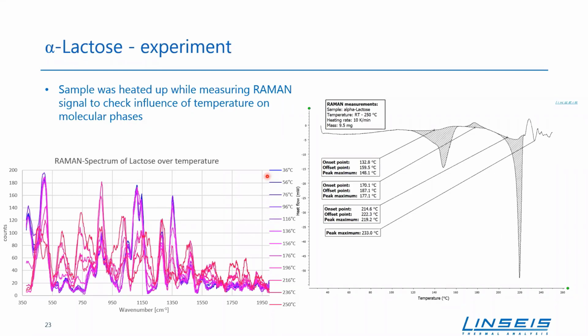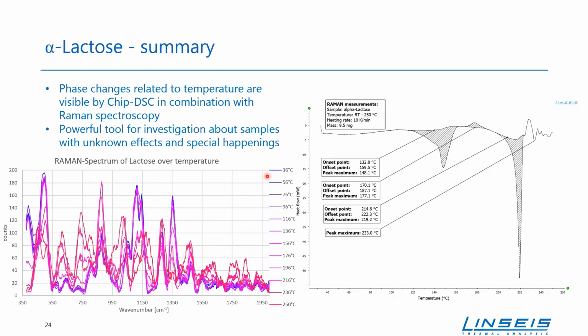So this is the result here on the right side. This is the measurement from our customer, and the last peak was quite strange, and they were wondering what happens there and for what reason. On the left-hand side, you can see the Raman spectrum of lactose over a temperature range, and these were the data we sent them, and they were happy. So what we can prove here is that it's really possible to check the phase changes related to temperature in combination of DSC and Raman spectroscopy. If you have a database or some further information about your material or Raman spectroscopy, this is a quite powerful tool for maybe some unknown effects or special happenings in your DSC signal.